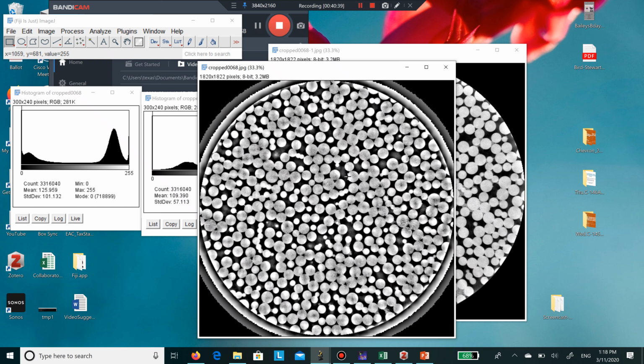But bear in mind what it is relative to in terms of your either grain size or pore size, so that when you say 40, you know that in this image it means a few grains. Right? So for these windows of averaging, median filtering and all those, always stay well below the dominant feature you're actually looking at, like grains or pores. So your noise should be below that, so to speak.